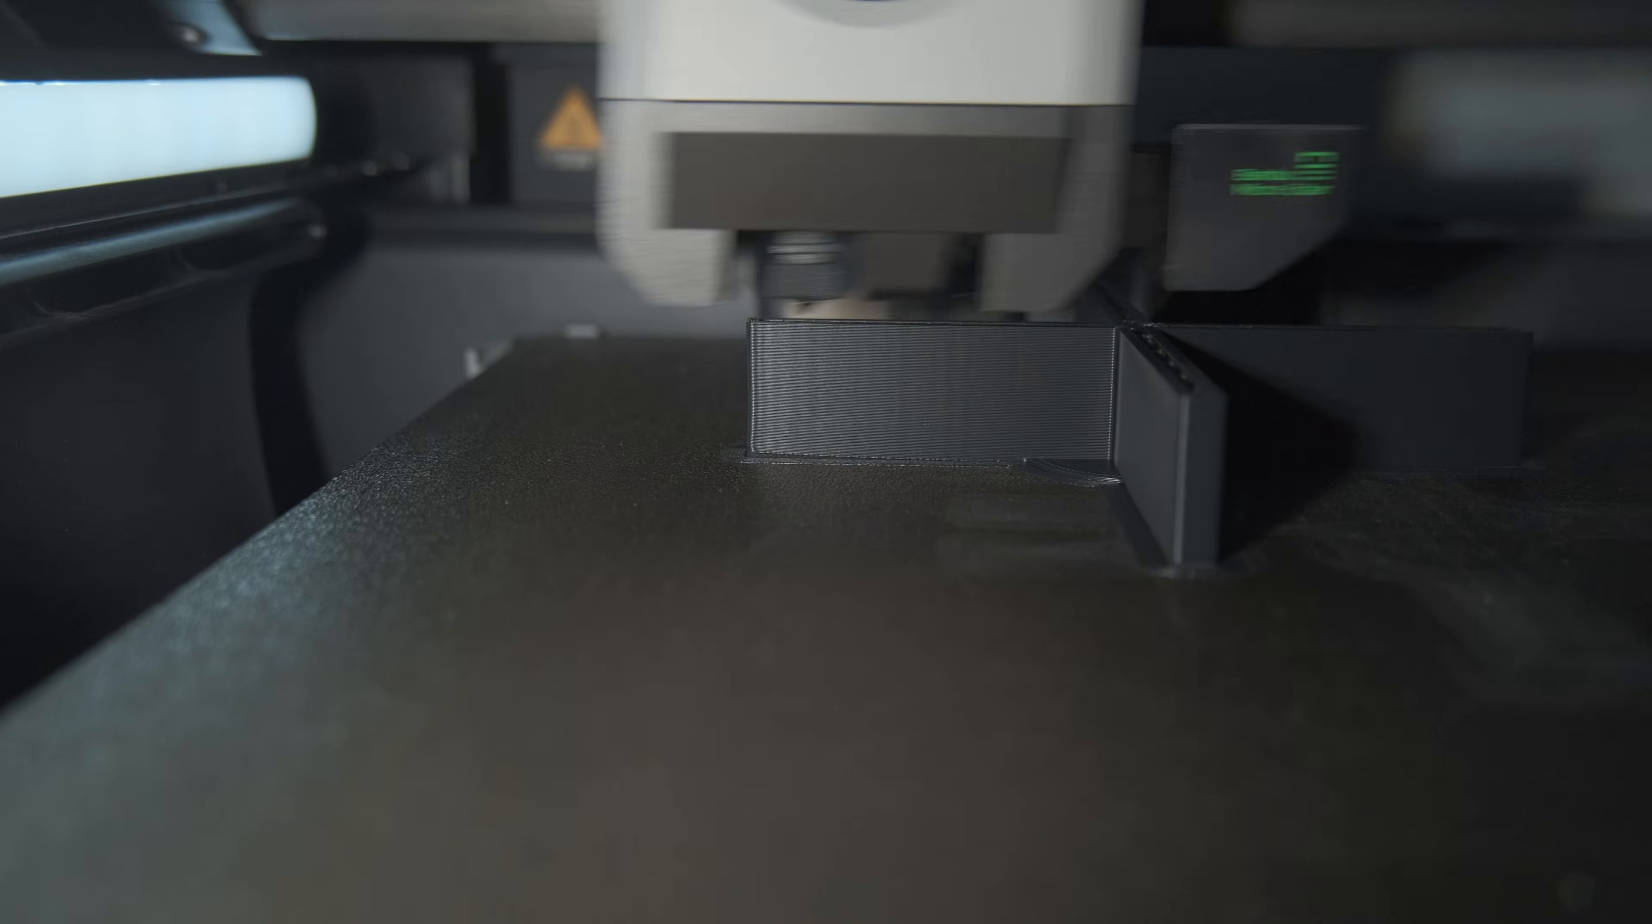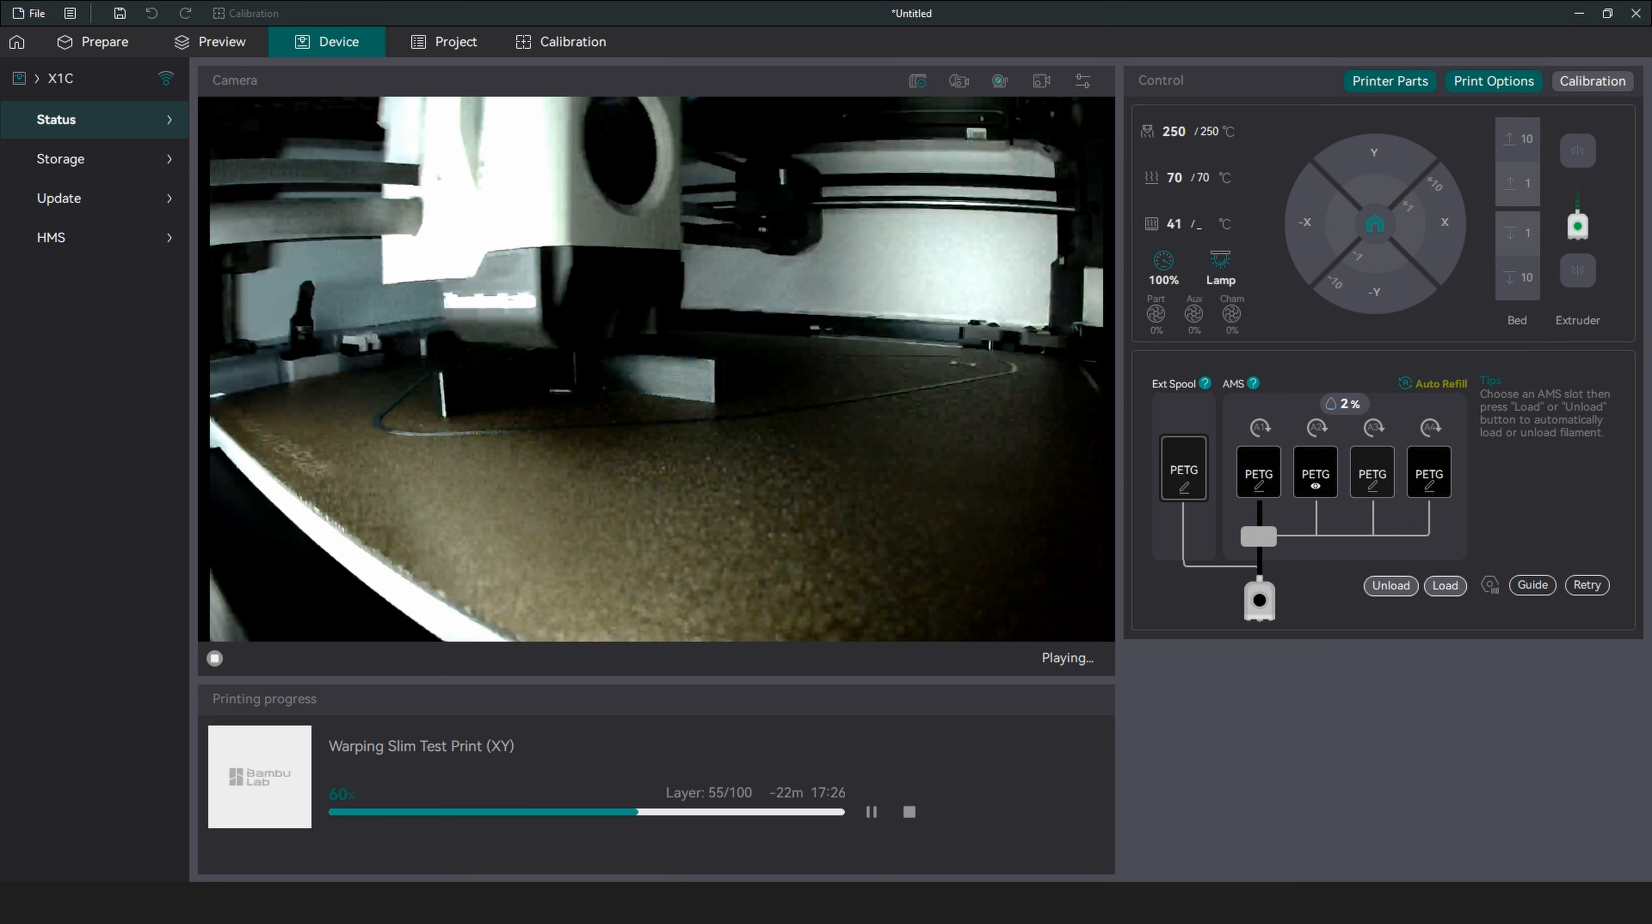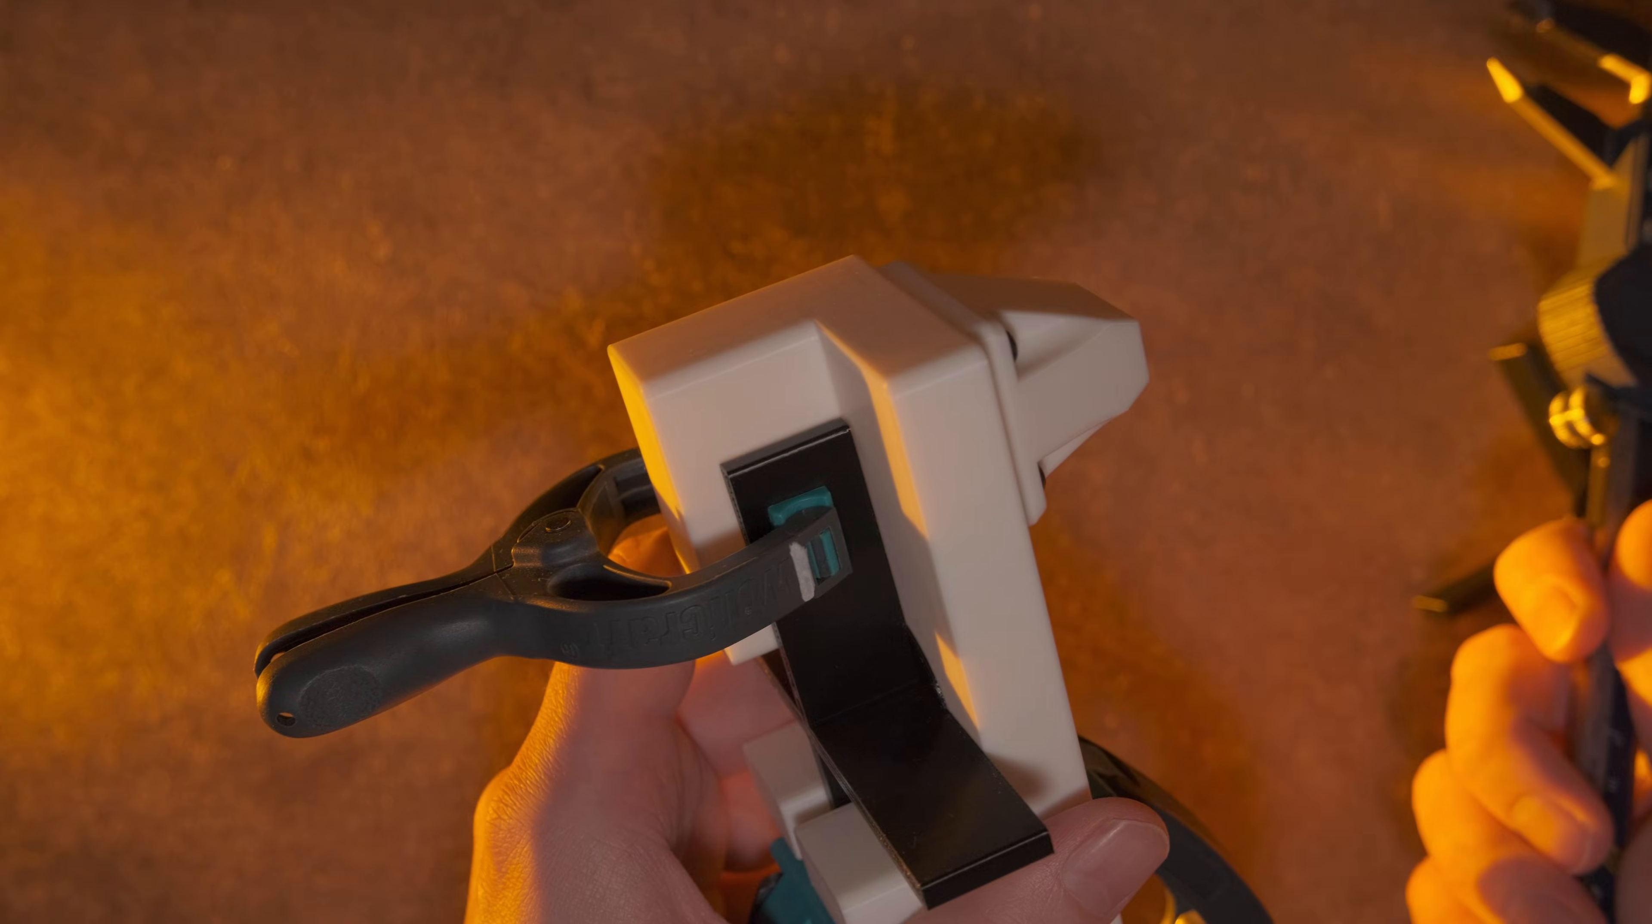Cooling can also be a huge factor for print warping, which can lead to dimensionally inaccurate prints or even worse. To test that, I make two thick prints: one printed more slowly without cooling and the other printed twice as fast at max fan speed. I wash the build plate before the prints and measure the warping of all sides with a custom jig.